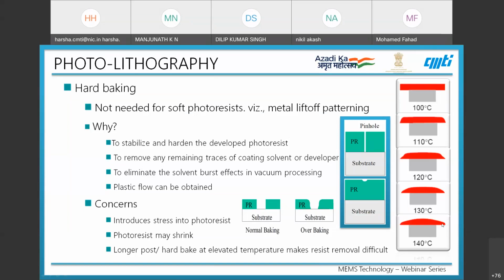The concerns with this process are that it introduces stress into the photoresist, and it may result in shrinkage of the photoresist also. And if we are doing this for a longer duration and at elevated temperatures, it makes resist removal very difficult.